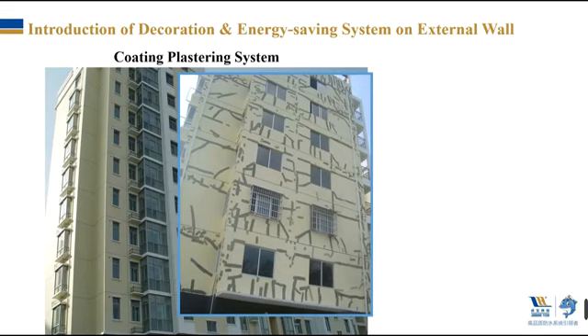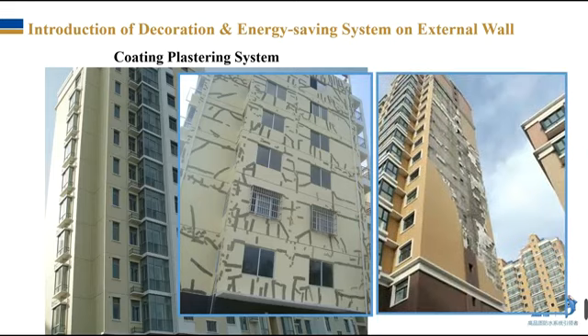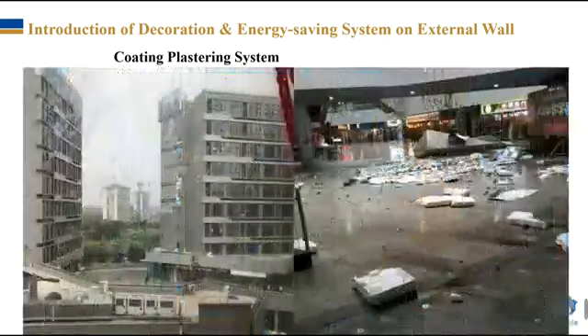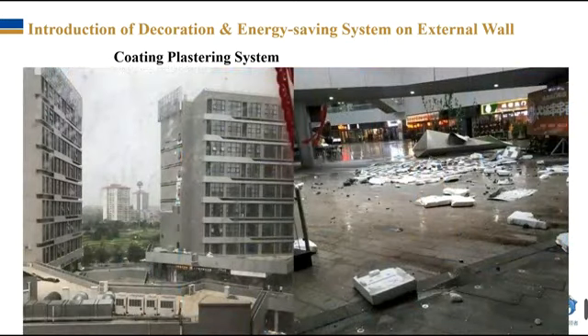Because this system is made of many structural layers, it is common to have cracking on the surface, as shown in the picture. Once the surface layer is cracked, the system will absorb and seep in water, and then bonding failure will occur, resulting in safety problems like the debonding between the decorative facing layer and the structural layer. These accidents happen very often these days, as you may see in those pictures.